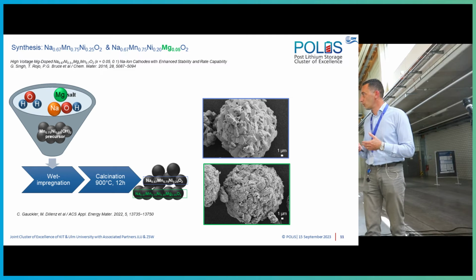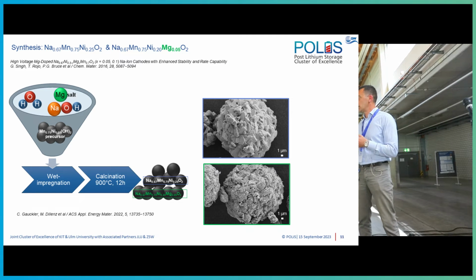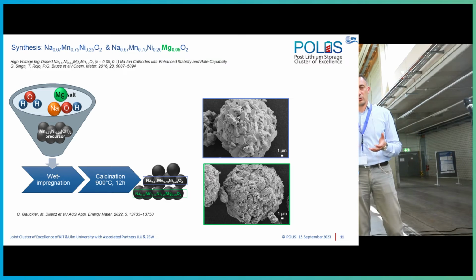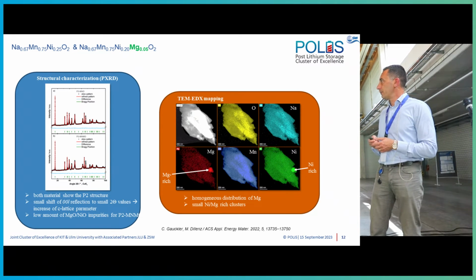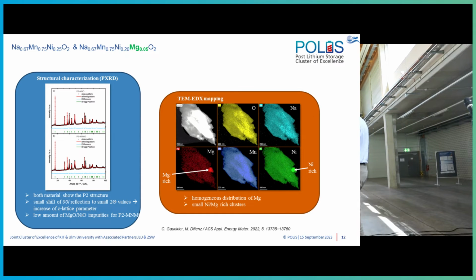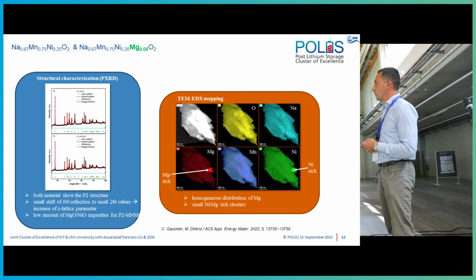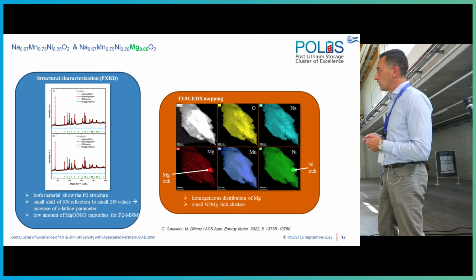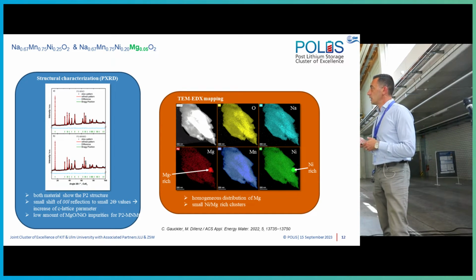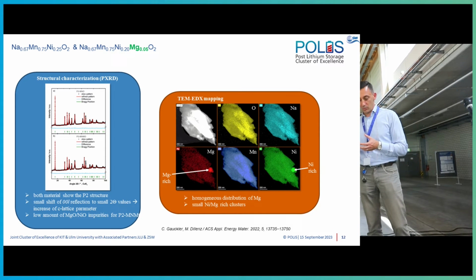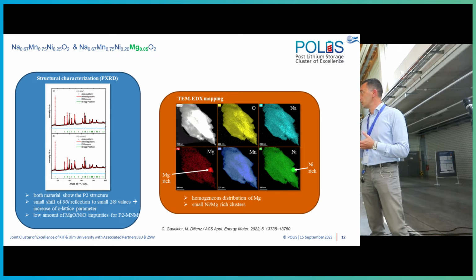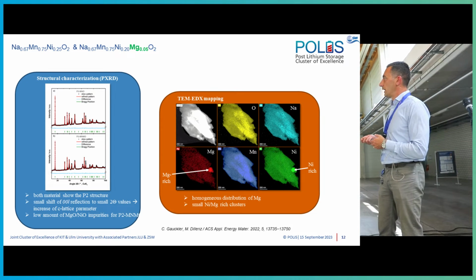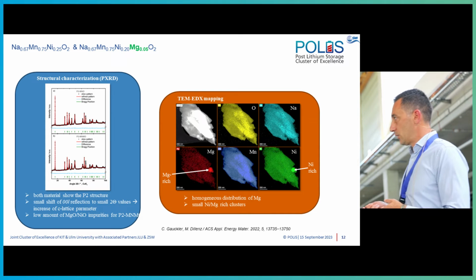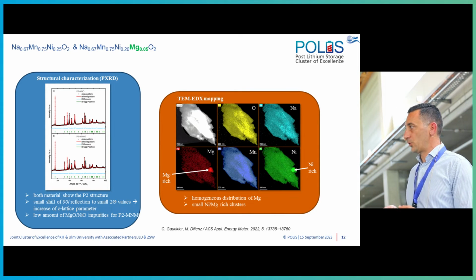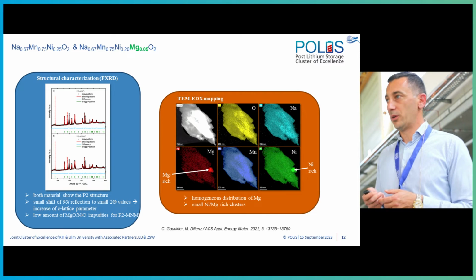We have a low amount of impurities in the doped material, and this has to do with the magnesium oxide and nickel oxide. Thanks to the Ute Kaiser group, we were able to image with the TEM, and what you can see is, I don't know if the color can be read so easily at a distance, that the magnesium distribution within the lamella that we have observed was quite even, although we could see a magnesium-rich and at the same time a nickel-rich spot, and this is pretty much in agreement with the impurity that we have found by X-ray diffraction.